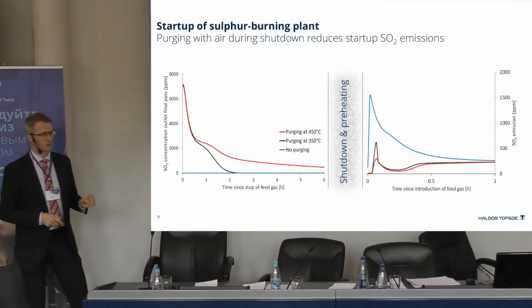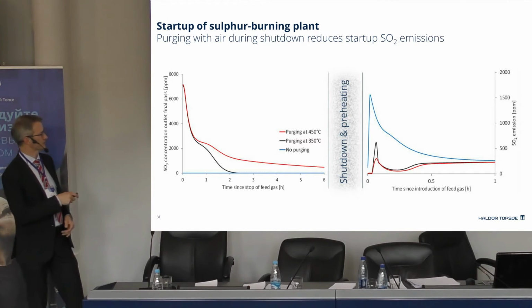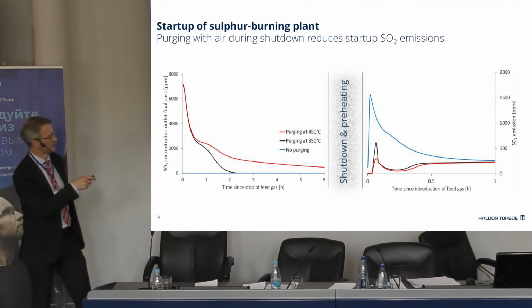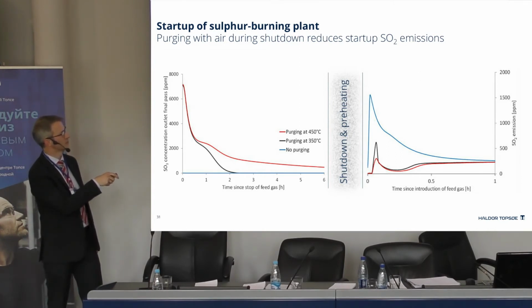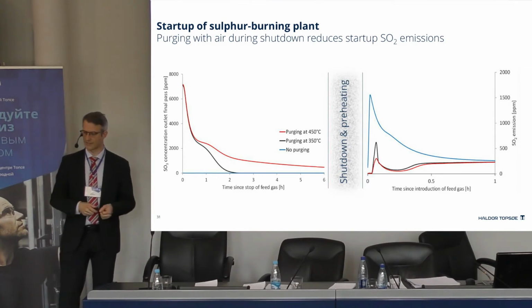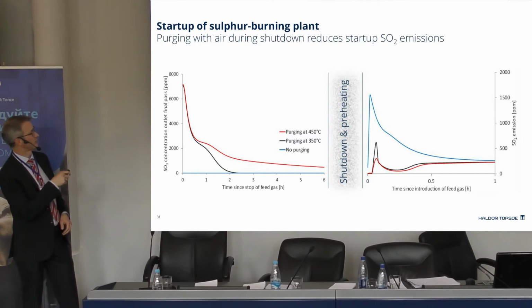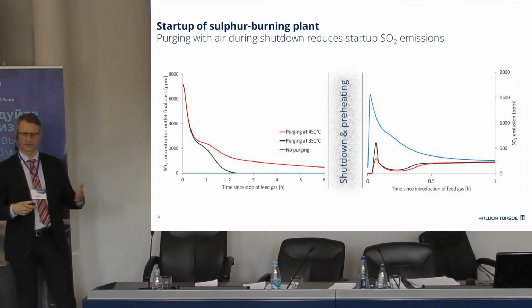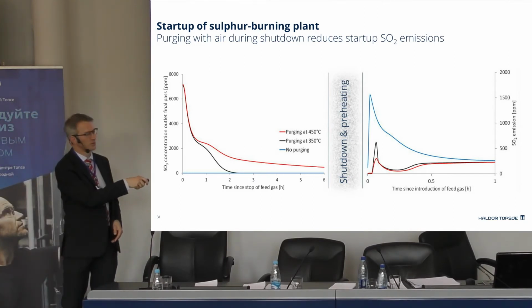So then we've used the model to say, how can we best operate a sulfuric acid plant? This is one case when a plant is shut down, it's normal to purge with air to get SO3 off the catalyst. And then you can see what happens when you start up the plant again, if you do it or if you don't do it. So here you can see how much SO3 comes off during purging. The blue one, you don't purge at all, so you have all the sulfur left in the catalyst. And then you can see the blue one on the right when you start up next time, you get a huge peak of maybe 1500 ppm SO2 going to the stack. However, if you purge, let's take the red one, purge at 450 degrees, you get a lot of SO3 off the catalyst during purging, and when you start up the next time, you will only have a very small peak in the stack. So in this way, we can calculate and derive better shutdown, purging, and startup procedures for the plants.